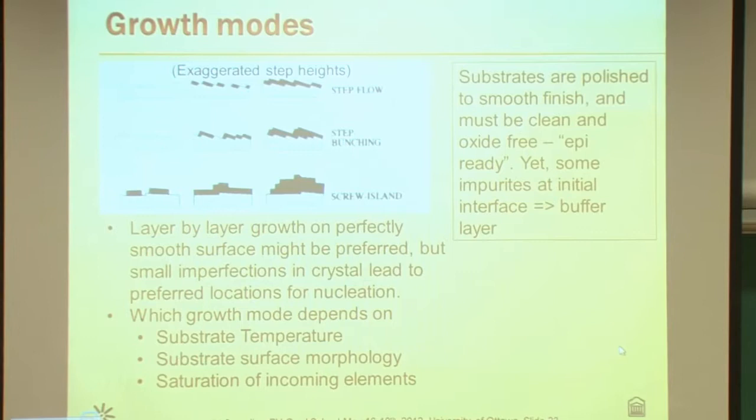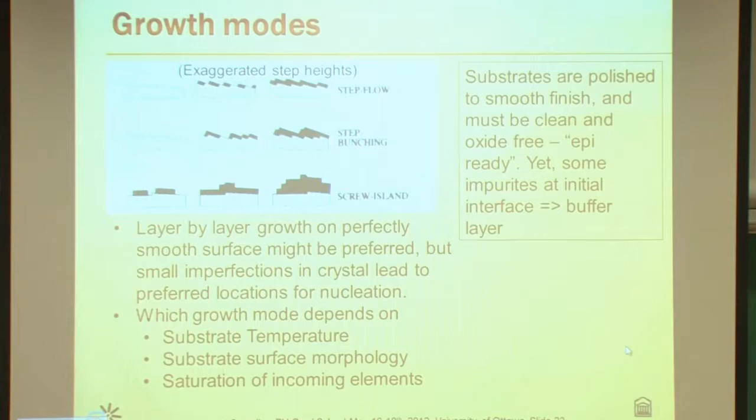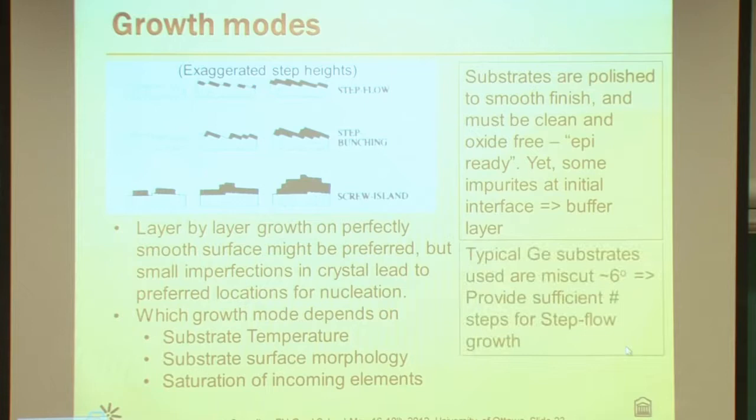So our substrates generally are polished to a smooth finish, and they also need to be clean and oxide-free, a term called epi-ready. And there's a certain cost associated with getting substrates epi-ready. And there are probably still a few impurities left at that initial interface, so there's typically a bit of a buffer layer thrown in when you switch from the substrate to your starting epi.